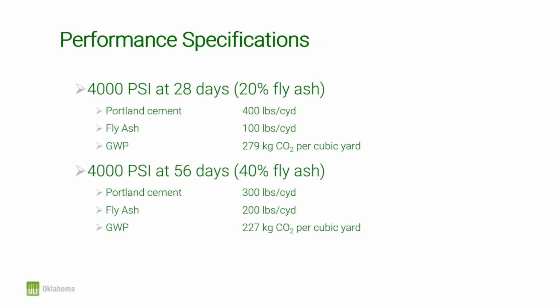One big thing that I want to show people is my 4,000 PSI at 28 days uses 20% fly ash, and my GWP, which is the global warming potential, is about 279 kilograms of CO2. But if you let me go to 40% fly ash and allow me to break that same 4,000 PSI at 56 days, now I can add a lot more of the fly ash that we are trying to use and drop the GWP by about 50 kilograms of CO2. So you see how we're starting to have an impact on how much we're releasing in that carbon footprint by playing around with the strengths and the time to get that strength.